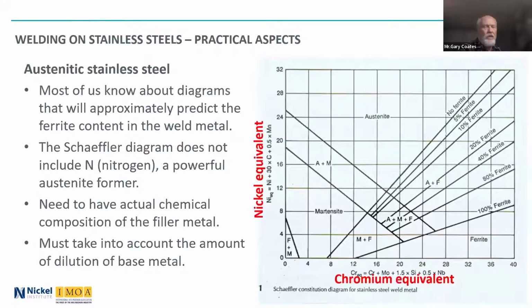So the vertical axis is, we call it the nickel equivalent, which is made up of both the nickel content, the carbon content, and the manganese content. Really, nitrogen needs to be in there, but it's really difficult to measure nitrogen that actually goes into the weld metal, because the arc, when you go from the wire to the base metal and transfer the droplets of molten stainless steel, they can pick up nitrogen. So you do make some assumptions about the nitrogen content there, and there are diagrams that include nitrogen. And of course, on the horizontal axis is the chromium equivalent, which is chromium, the molybdenum, silicon, and to a very minor extent, the niobium content.